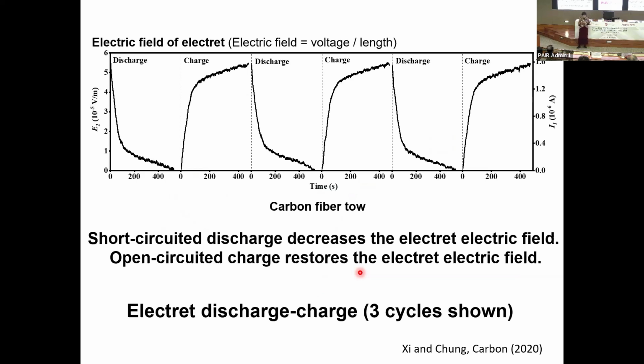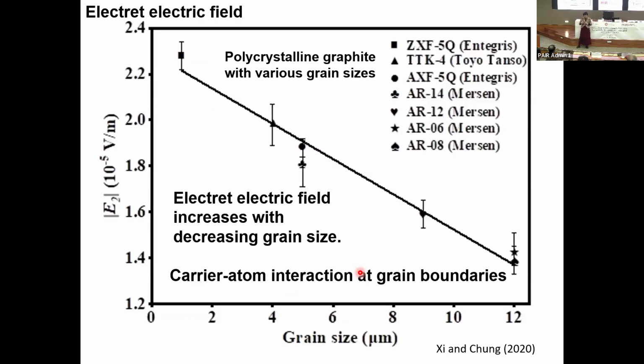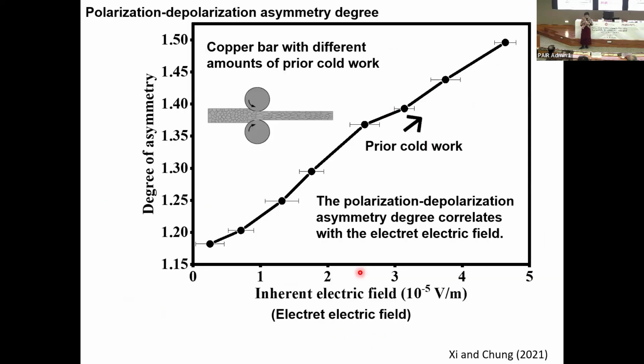This is the result for a carbon fiber tow, showing 3 cycles of discharge and charge. So again, short-circuited discharge would kill the voltage, and then after that, open-circuited charge restores that voltage. The electric field inside the electret gets bigger as you decrease the grain size. Another indication of the interaction between the electrons and the atoms, particularly at the grain boundaries.